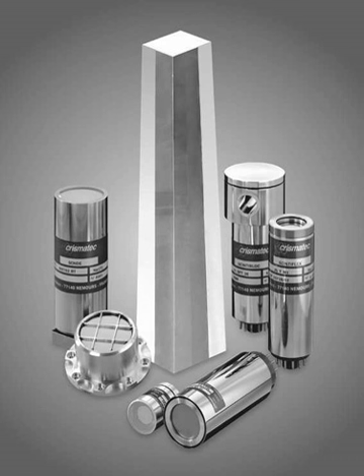The light output is often quantified as a number of scintillation photons produced per keV of deposited energy. Typical numbers are, when the incident particle is an electron, approximately 40 photons/keV for NaI(Tl), approximately 10 photons/keV for plastic scintillators, and approximately 8 photons/keV for bismuth germanate, BGO.